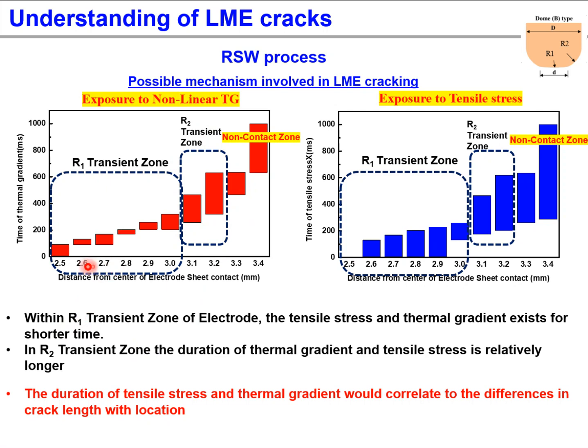In the R1 transition zone of the electrode, the tensile stresses and thermal gradient exist for a shorter time. In the R2 transition zone, the duration of thermal gradient and tensile stress are relatively longer. So the duration of tensile stress and thermal gradient would correlate to the differences in crack length with the location.